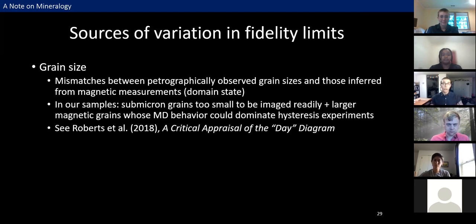Okay, so we've talked a little bit about grain size, and long story short, we see interesting mismatches between petrographically observed grain sizes and those that are often inferred from magnetic measurements by way of domain states. And in our samples, we observed these two different populations of iron nickel grains that we wouldn't have been able to differentiate from hysteresis experiments alone.